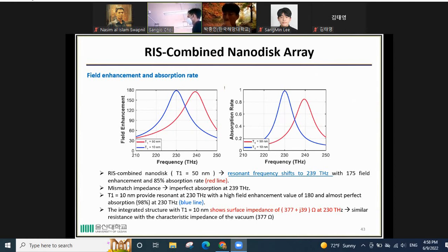Yeah, that's mentioned in the literature. And my question is, do you know the reason why, when we include the RIS substrate, the antenna characteristics are shifted? Actually, Professor, for the absorption rate, as I mentioned before, when we put the RIS underneath the antenna, the magnetic response is higher compared to the antenna sitting directly on the silicon dioxide substrate. So this magnetic response because of the RIS can capture the incident radiation, so that perfect absorption is achieved.